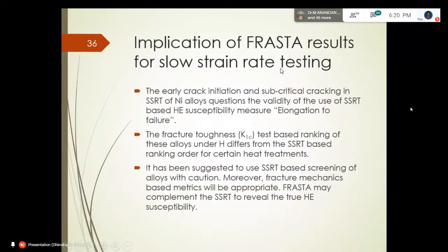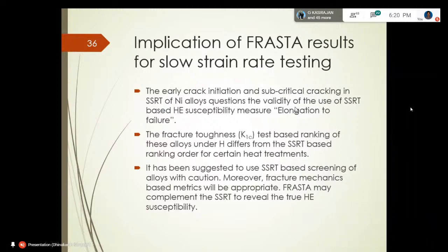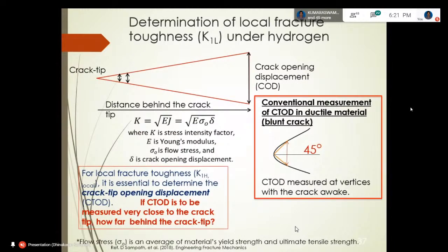of FRASTA. So what are the implications? Early cracking, crack initiation, and subcritical cracking are observed in the slow strain rate test, which is not a better way of evaluating the susceptibility. So we need to go for fracture mechanics based tests. And also, we did some fracture toughness tests and compared with the results from SSRT for ranking purposes. For certain heat treatments, we didn't see the same order of ranking. So that's the message. We need to use fracture mechanics, but I think we can also use this FRASTA technique